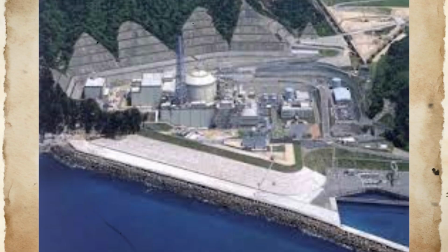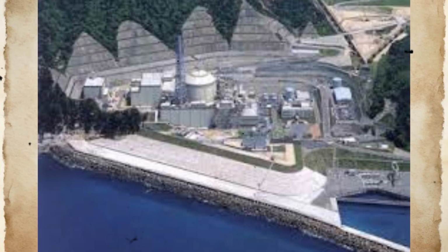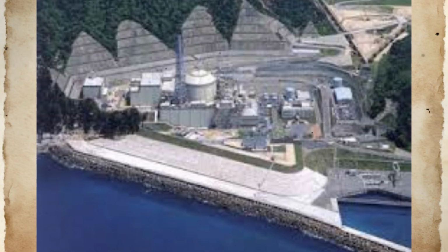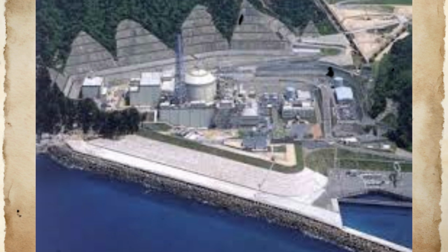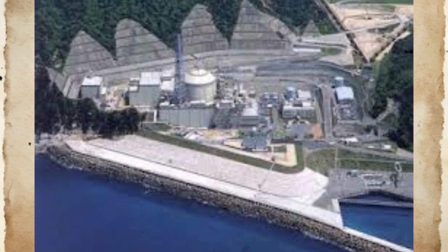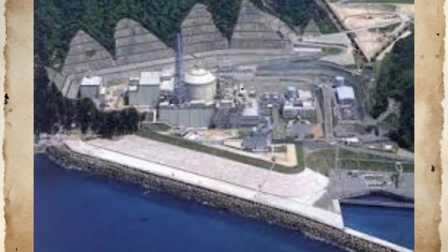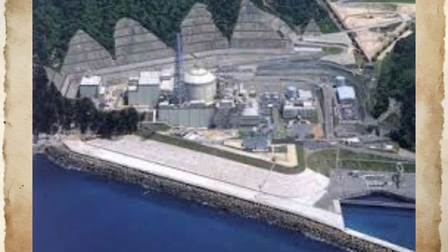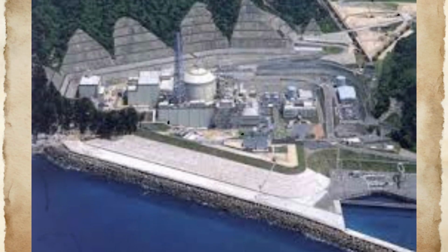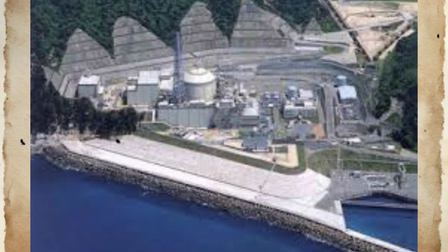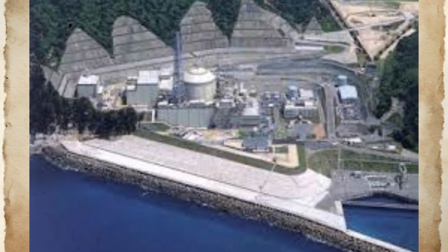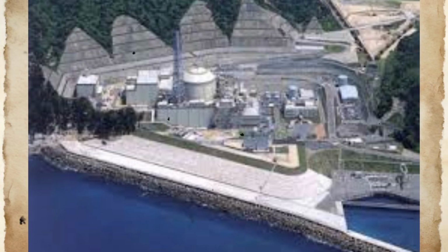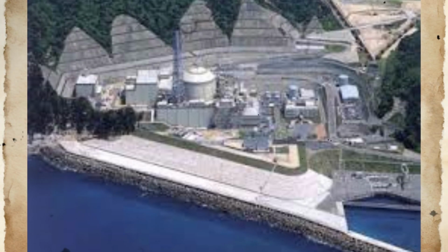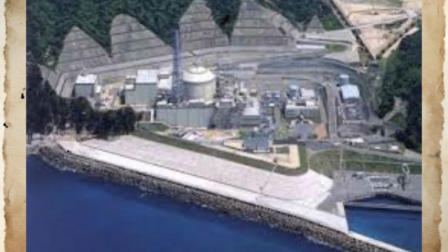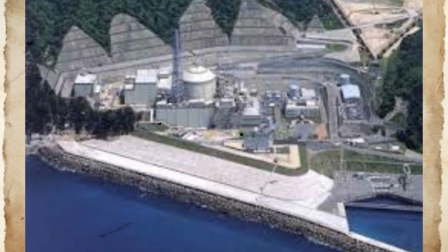Immediately after reactor trip, decay heat removal was established through the auxiliary cooling system for all 3 secondary loops. This configuration provided adequate cooling capacity, while allowing operators to begin isolating the affected Loop C. Decay heat levels at 43% power required substantial cooling capacity, but the 2 intact secondary loops provided sufficient heat removal capability with ACS support.